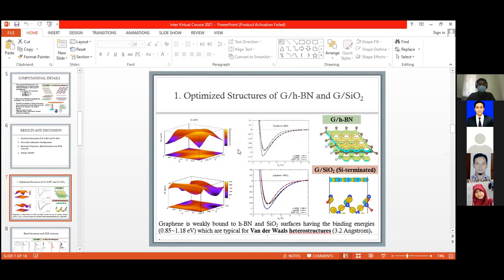By combining the two results shown in these figures, we can find the minimum energy configuration of graphene on the substrate, in this case hBN. Here I hope you can follow the lattice constant of the substrate. You can vary both the lattice constant and the different possibilities of how graphene can lie on the boron nitride. The graphene you create here uses the lattice constant of boron nitride.